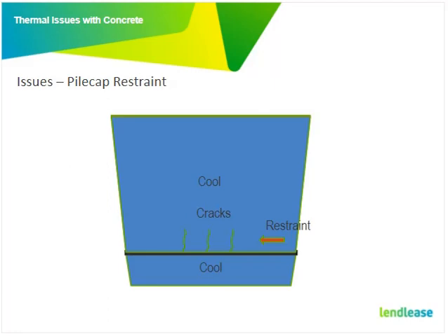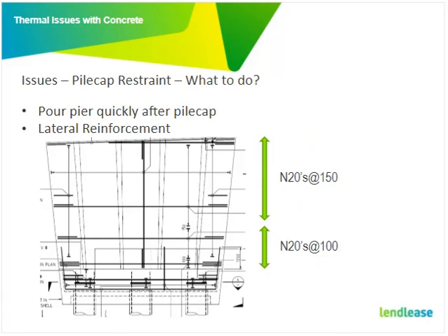So talking about differential temperature here, I suppose I should explain the issues that can occur. This is on the same job. You've got a pile cap that you've poured, and then you've gone and put another concrete pour on top. It gets hot. You've got a restraint there, so it wants to shrink as it cools, and as you can see, that's where you typically see some cracks. What did we do on this job? We had a requirement to pour the pier quickly after the pile cap. And we also used a higher density of reinforcement at the base.